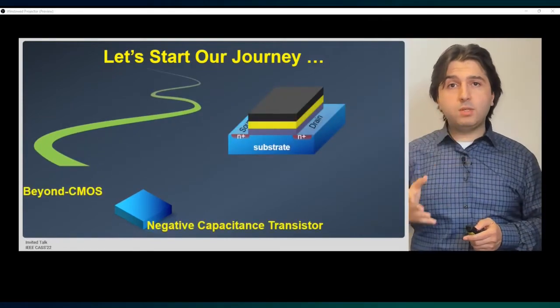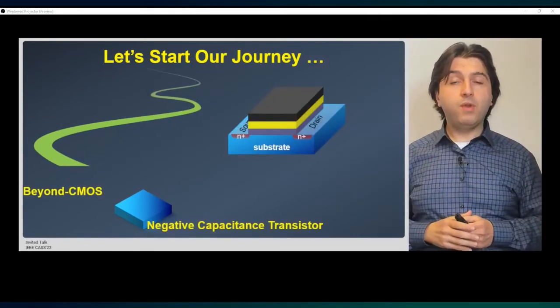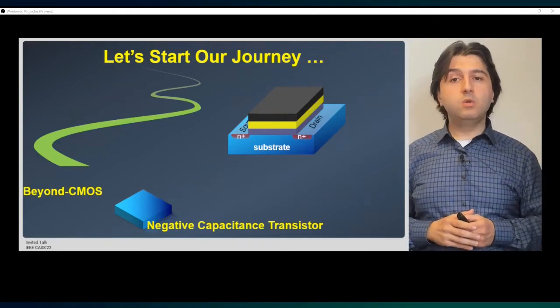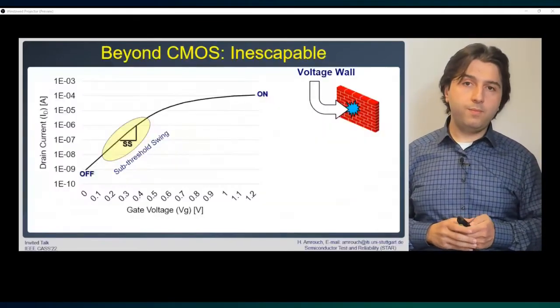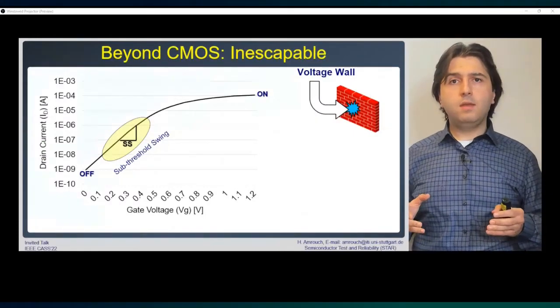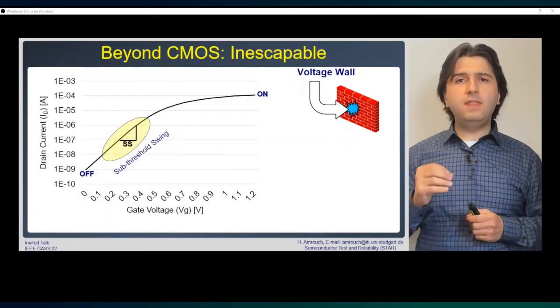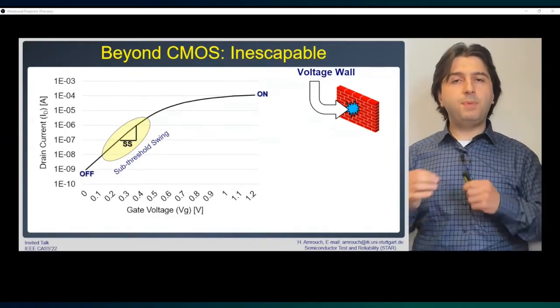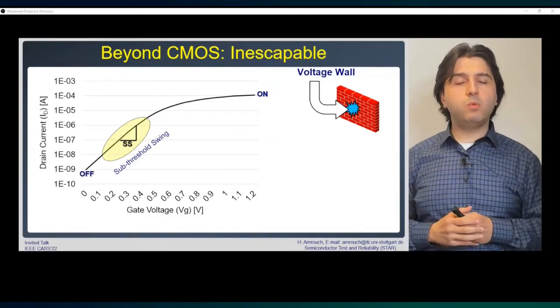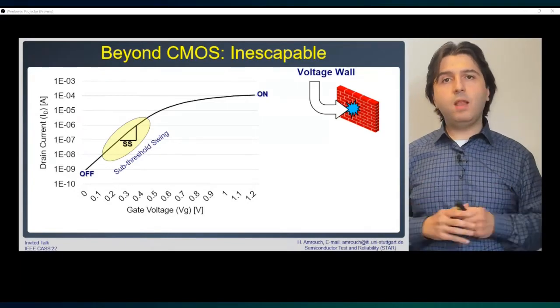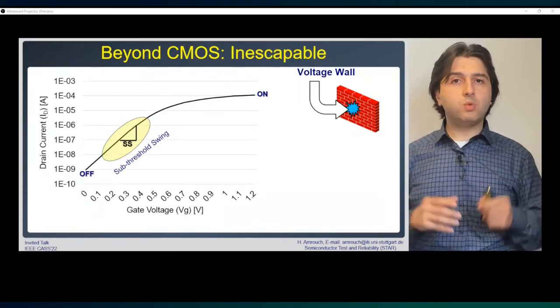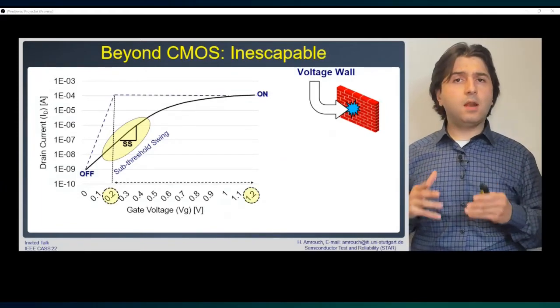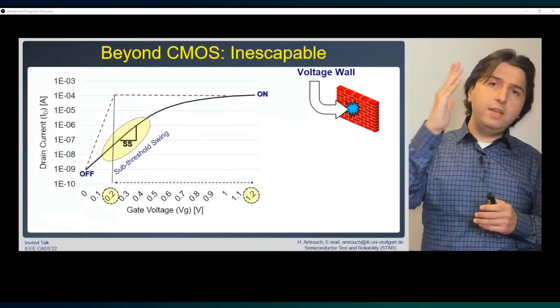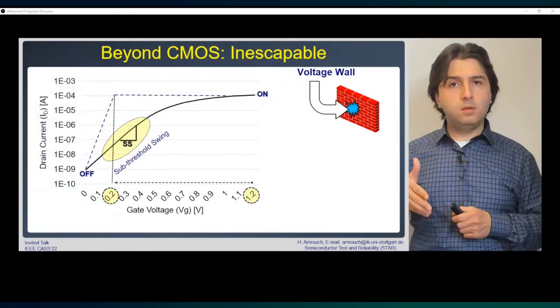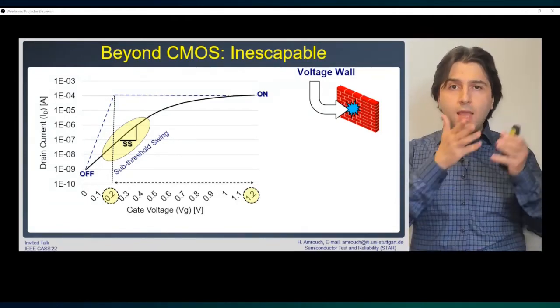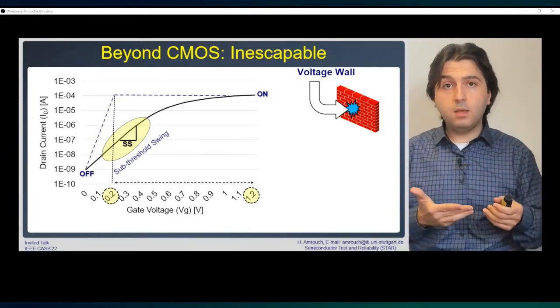And beyond CMOS technology, I will pick up one of the very promising technologies nowadays, which is the negative capacitance transistor. We all know that in semiconductor physics, there is a fundamental limit in the way we can switch the transistor between off and on state. This is well attributed to the so-called sub-threshold swing. And if we could build a transistor that features a much steeper slope, then we would be able to achieve the same on current, hence the same performance, but at much, much lower voltage.